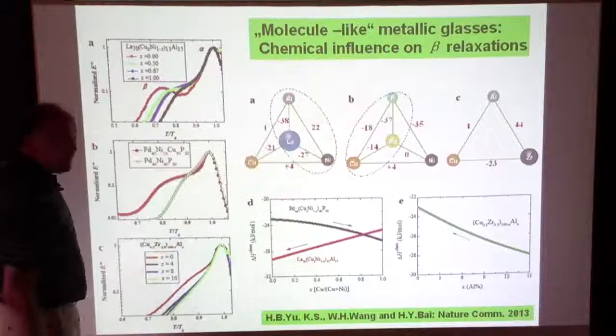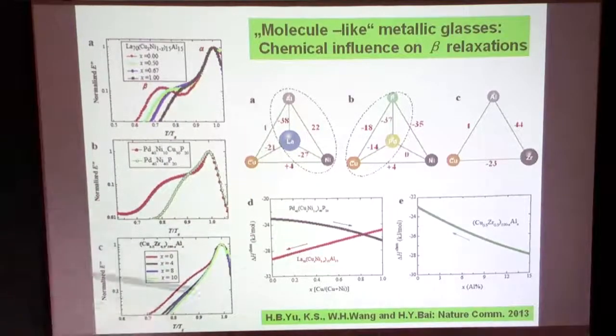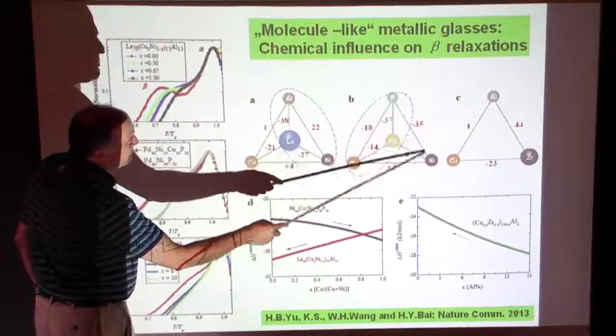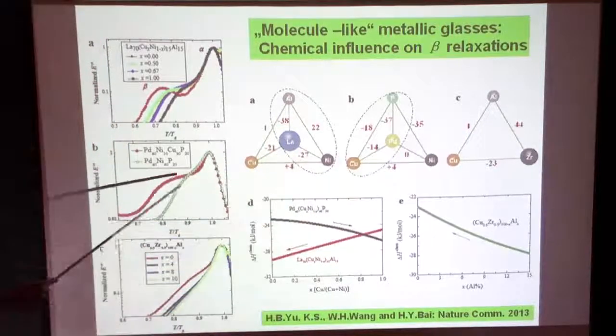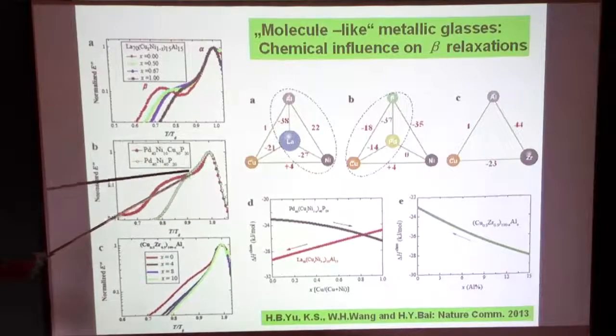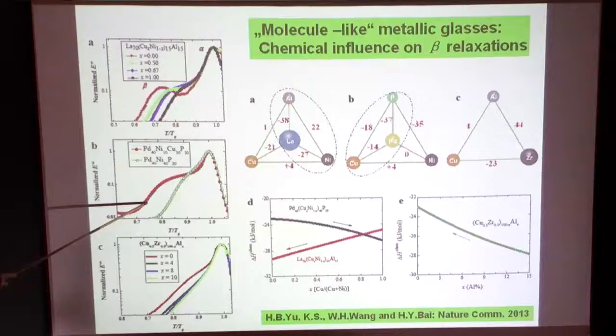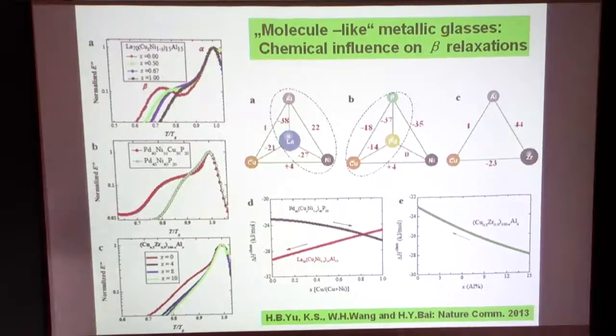They are all arranging in a certain way like a molecule. If we now add nickel to it, which is plus compared to copper and 0 to palladium, strong heat of formation to phosphorus, then you see, for example, that this is the nickel, and if you add copper to it, then you have this one here, a strong peak. The idea is the following: we're talking about metallic systems, where normally you think about an S-like electron distribution, which has typical metallic bonding. It's not the case. We have strong orientations between the different bonds.